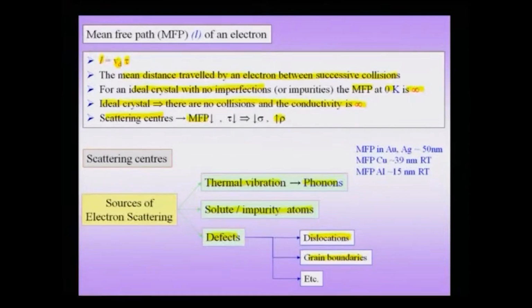And therefore, instead of the mean free path being infinity, the mean free path typically reduces to a very small number. For a good conductor like gold or silver it is about 50 nanometers. On the other hand, even for a slightly less conducting material like aluminum, the mean free path has already reduced to about 15 nanometers. The mean free path for copper is about 39 nanometers. Clearly, you see that the mean free path is of the nanoscale. So automatically the question which comes to our mind is: suppose I have a nanocrystal of the size of the mean free path, then what happens to its conductivity? This is the question which we will try to understand very soon.